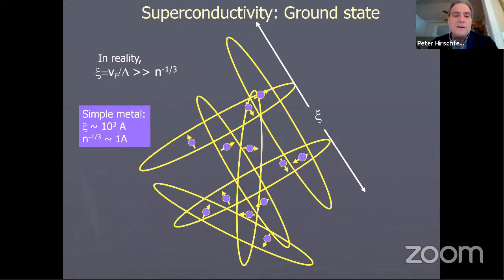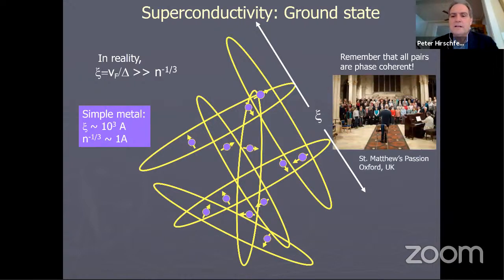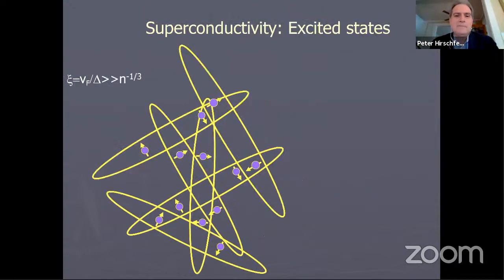In a simple metal, the size of these pairs is going to turn out to be 1,000 angstroms, tin, for example, and the distance between electrons on the average is about an angstrom. So you have a picture of a lot of interpenetrating pairs as the true ground state of the superconductor, and you have to remember that they're all phase coherent, like St. Matthew's Passion in Oxford.